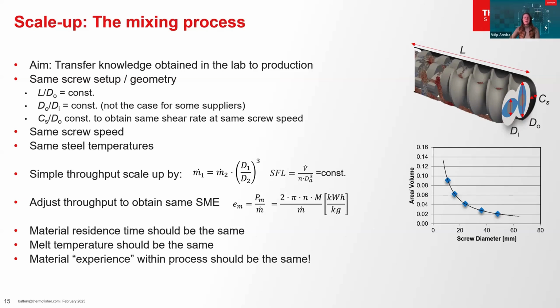Then we should use the same screw speed in both settings to maintain the same mixing intensity. Maintaining the same steel temperature is important to ensure thermal consistency throughout the process. But have in mind that the heating surface to volume ratio drops with increasing screw diameter, as shown here in the graph on the right.